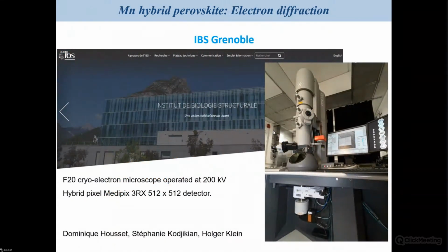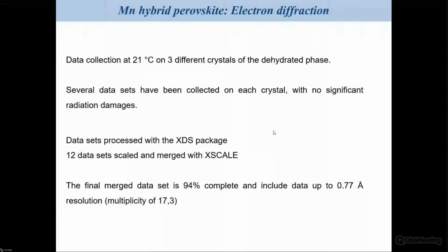And to confirm that it is a good structure, we asked colleagues from Grenoble, Dominique Housset, Stéphanie Kodjikian, and Holger Klein, to make measurements on very, very small single crystals to extract the structure of the material after the first heating. As you know, electron diffraction is something which is very destructive for your samples, and they needed two different crystals to be able to collect enough information for what we are interested in.